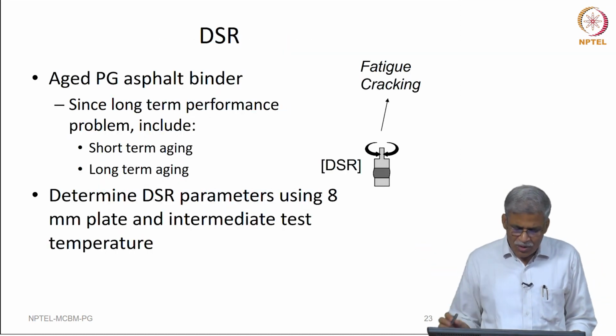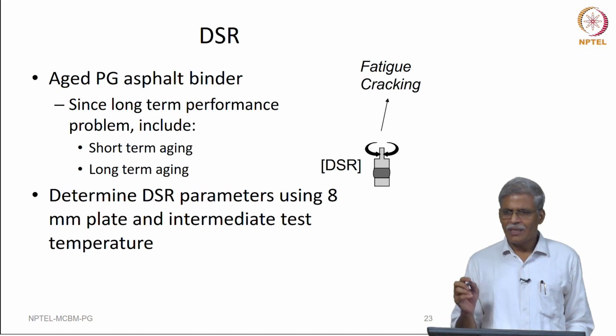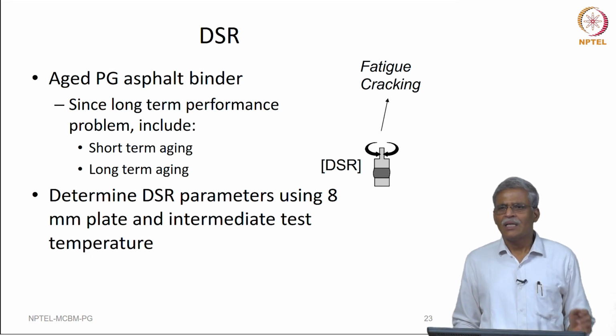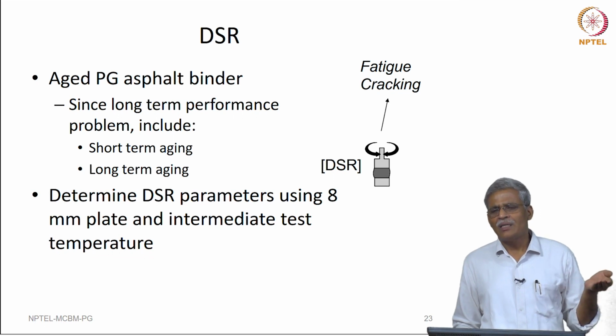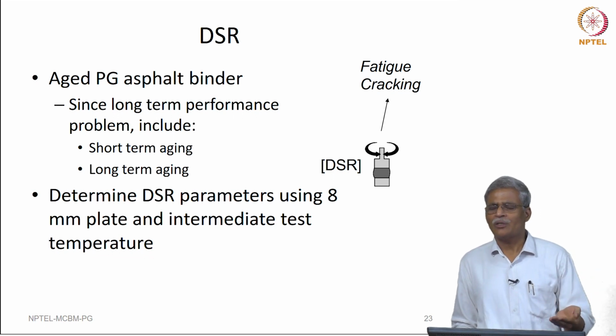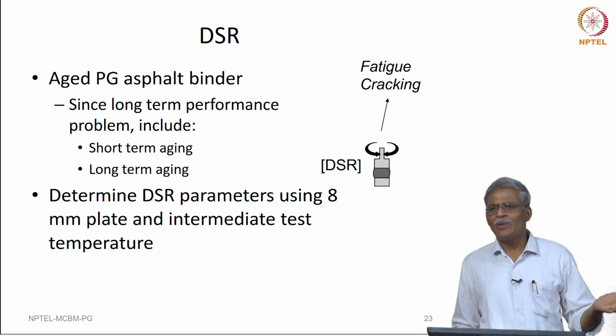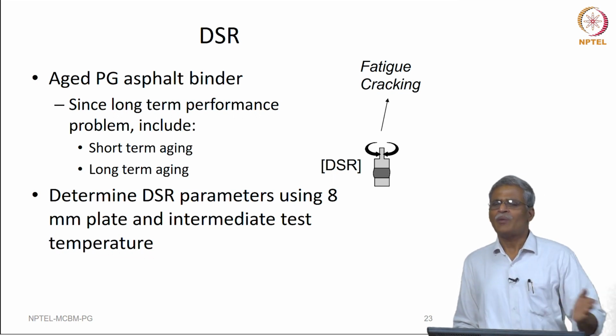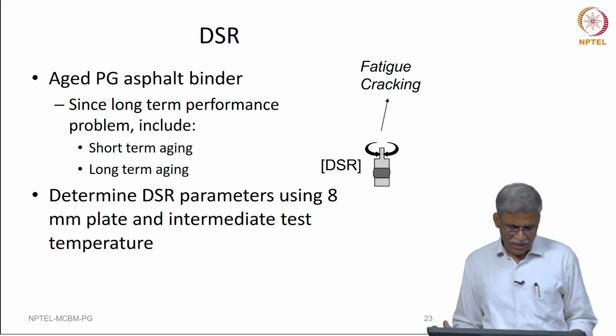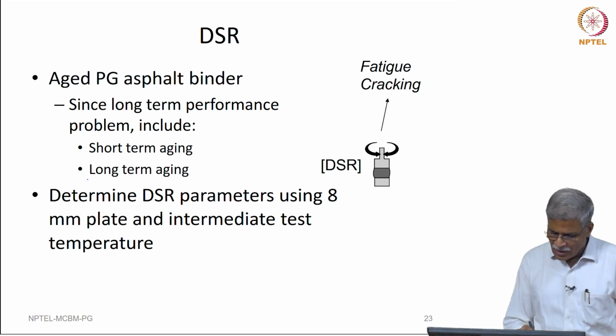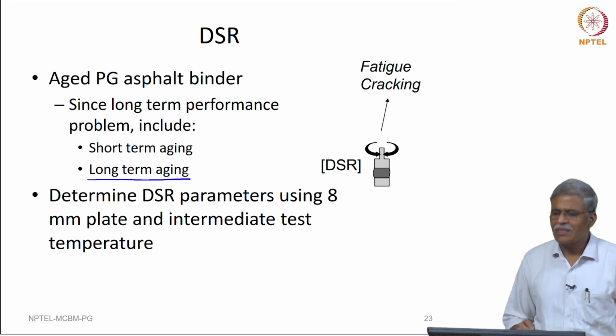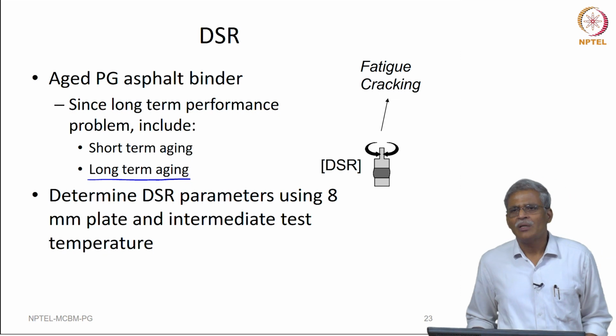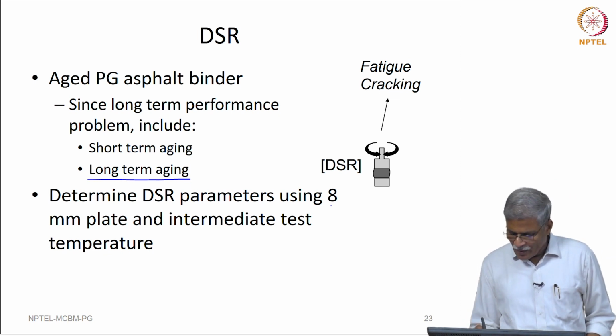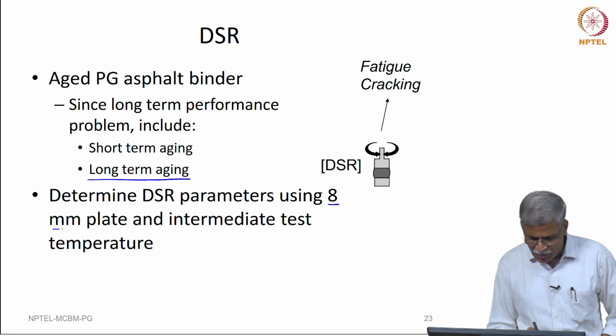So we do this testing under different aging conditions. Since it is generally expected that these kinds of cracks that you saw in the earlier slide happen after some period of construction, this test is carried out on bituminous binders that have been subjected to long-term aging and using an 8 mm plate.